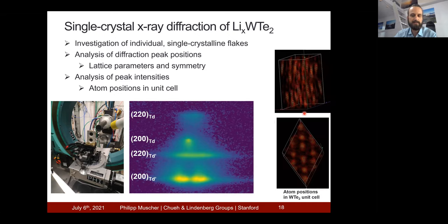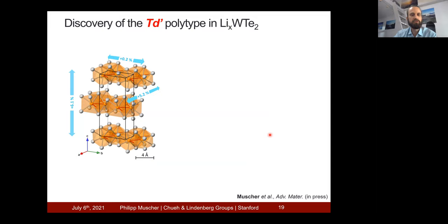So by using this technique, we can get these electron density maps of the tungsten ditelluride unit cell, where the bright areas correspond to where the atoms are sitting. Using this technique, as well as bulk powder X-ray diffraction, as well as density functional theory, we confirm the structure of the new phase that's being induced by lithium ion insertion. It turns out it's a structure that has never been observed before, and therefore we call it the Td prime polytype. As the material transitions to this novel structure, we have a large scale out-of-plane expansion by 6%, which you can imagine as you put ions in between the layers, they will expand. But much more interestingly, we also have a 5% in-plane expansion, but only along one of the in-plane directions, not along the other.